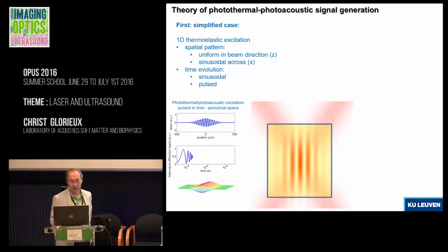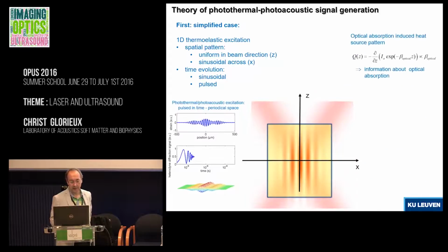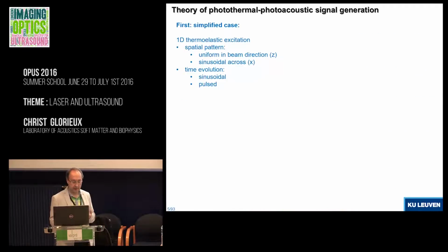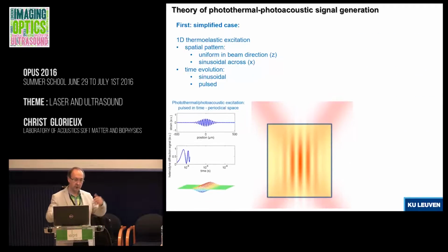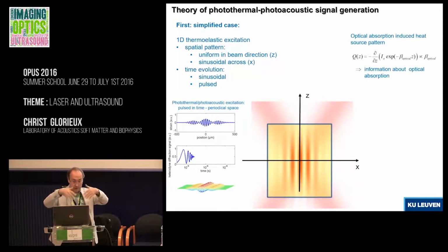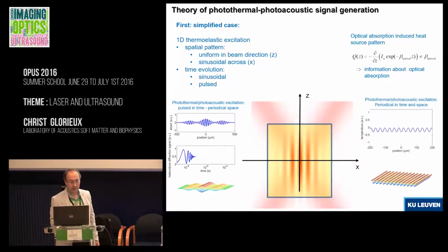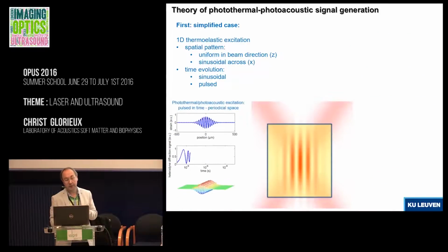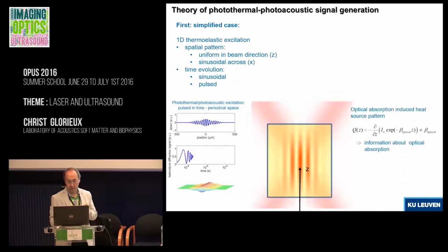Here you look at the displacement. You see that there's a kind of average displacement, which in the beginning is the thermal expansion. And on top of that, because you have crossed laser beams, you have a sinusoidal grating, and you have waves which are moving, so you also see some sinusoidal aspect. That's a nice thing about photothermal and photoacoustic signals, that they have the two in one.